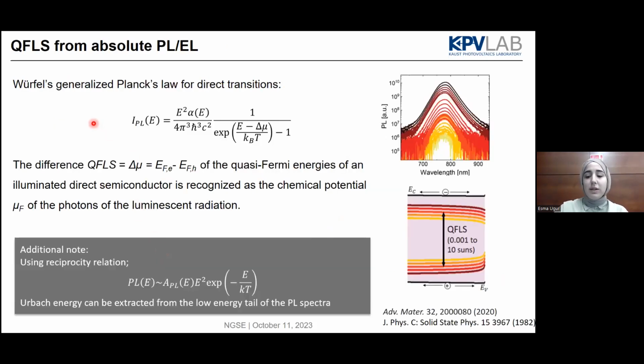So how we are getting this quasi-Fermi level splitting is basically like that. We are getting the PL spectrum, and using the Rau-Wurfel generalized Planck law for this direct transition, we are measuring the absolute PL, and we are extracting this quasi-Fermi level splitting that gives you information about the potential open circuit voltage of your sample or device stack. I mean, whatever you have as a sample. And also from using this reciprocity relation from the low energy tail of that PL, we can also get the Urbach energy, which is also an important parameter, especially if you are dealing with new compositions.